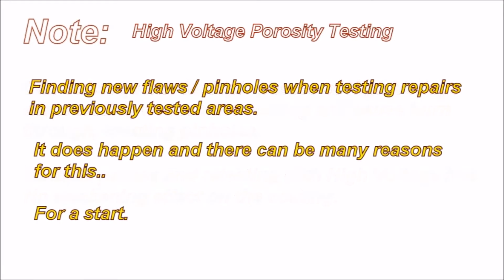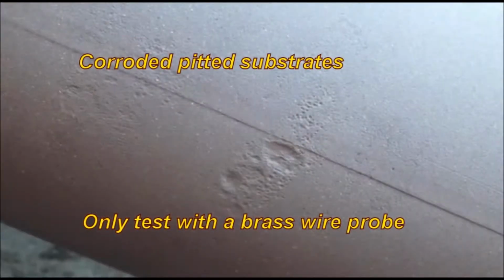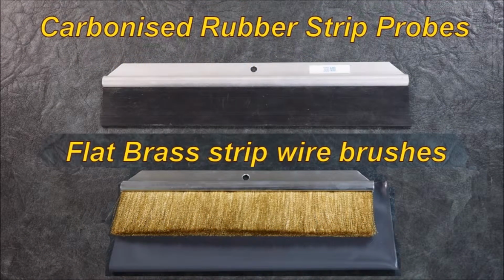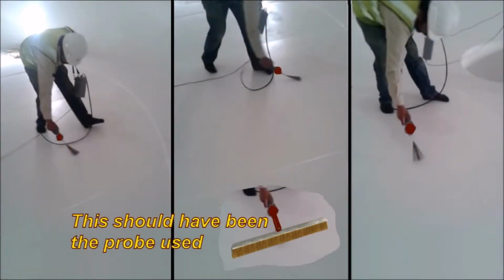Finding new flaws, pinholes, when testing repairs in previously tested areas. It does happen, and there can be many reasons for this. For a starter, let's look at some of this. Heavily corroded substrates: only test with a brass wire probe. These fall into the holes. The carbonised rubber strip probes will not fall into the indentations like a brass strip wire probe will. This should have been the probe that was used here, not a little fan brush. As you can see, there's going to be a terrible amount of missed areas, and on retesting you'd most likely find all the spots not covered before.